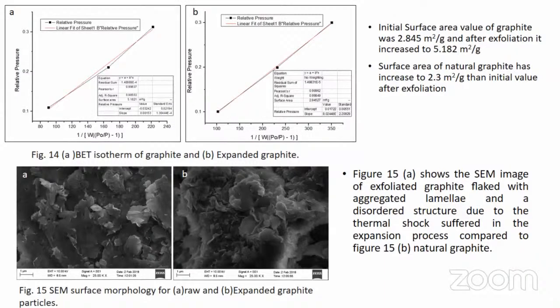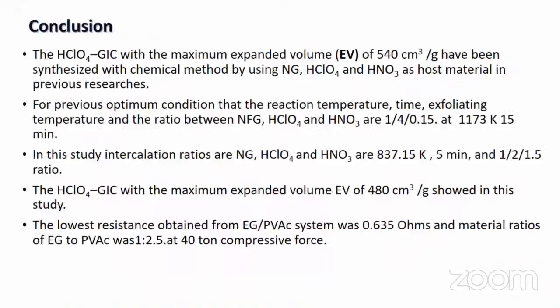The first value for the raw graphite is 2.85 square meters per gram, and it increases to 5.182 square meters per gram. These are the nitrogen adsorption plots. Also in figure 15 we can see the surface morphology of the expanded graphite and raw graphite. In the first image we can see a low amount of flake-like structures on the surface, but after the exfoliation we can see a high amount of flake-like structures in expanded graphite.